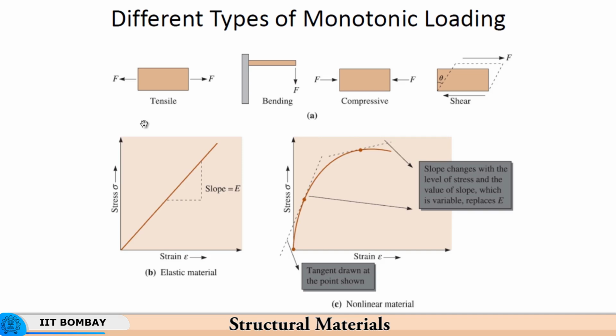Here you have the stress strain relationship where the slope E is constant, here the slope E is varying. Now, in this kind of mechanical behavior, the slope of the tangent depends upon where the tangent is drawn. If you draw a tangent somewhere there, the slope is very much different as compared to the slope over here, and therefore, the extent of deformation also governs the rate of hardening, as it is called, because when you say the stress is increasing with strain, we call it rate of hardening of the material with respect to strain. So, essentially this will be a measure of strain hardening of the material.